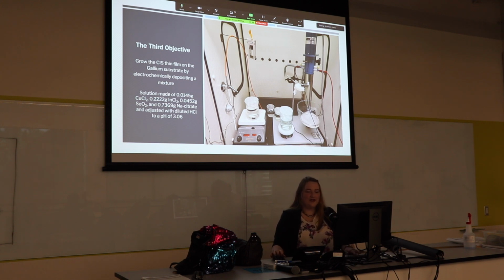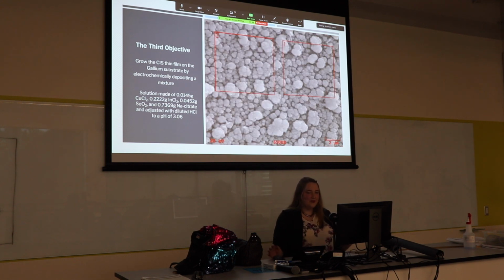And after all of this, we did see a beautiful film form on top of our gallium, which was great. We weren't sure if the film was going to actually form on top of the gallium or not. So good news that we can actually see this beautiful film.